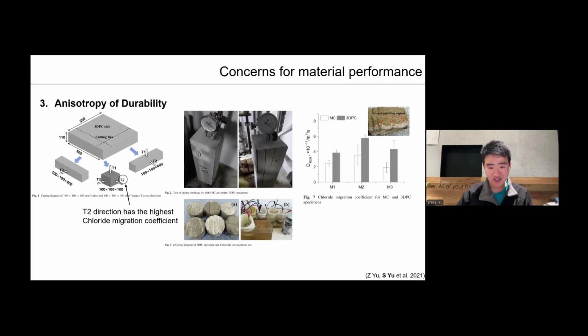The difference once again comes back from the void structure. As I explained earlier, the printed concrete has directional pores due to the pumping and extrusion process. And these make chloride ions migrate more easily in certain directions. So for designers, this adds more complexity to the design. It's not enough to think about the mechanical strength alone. Durability and anisotropy must be considered during the design stage.